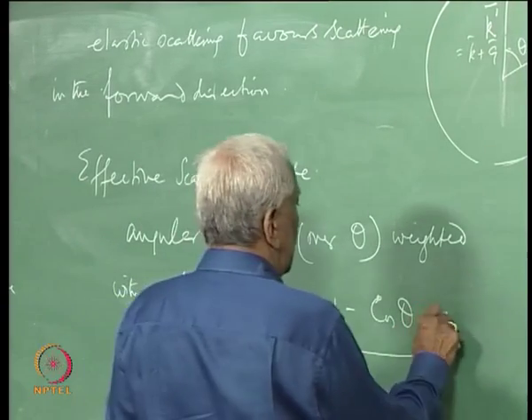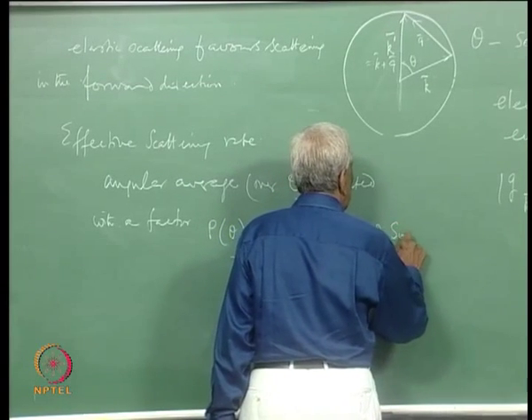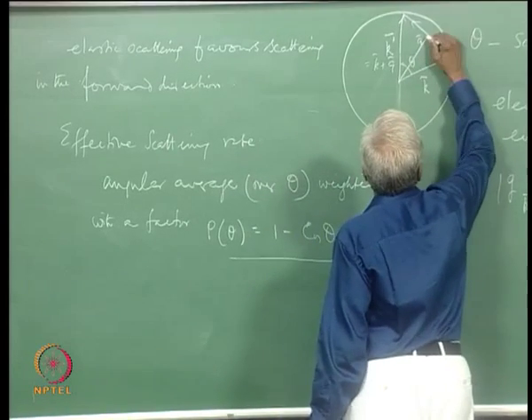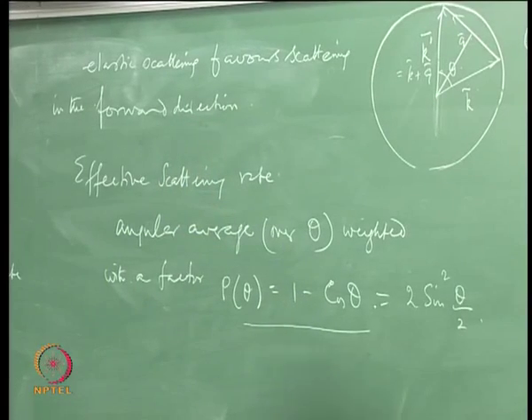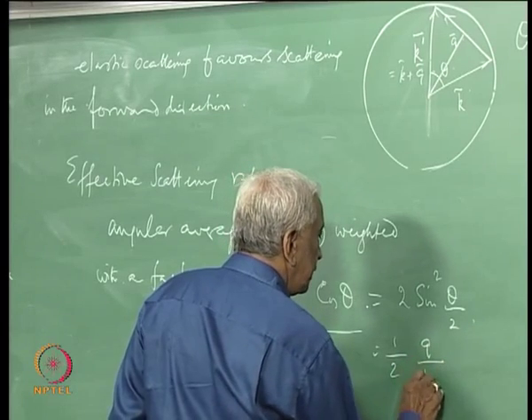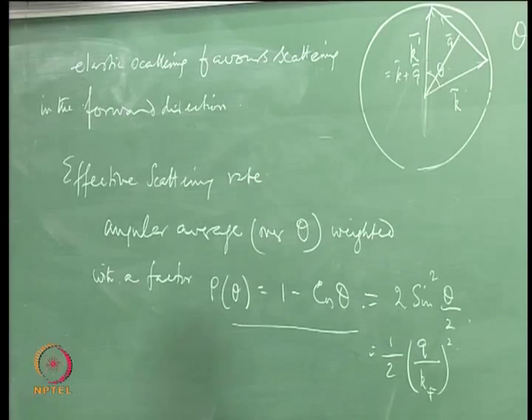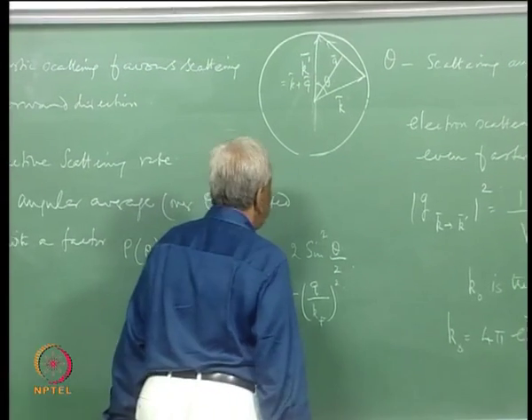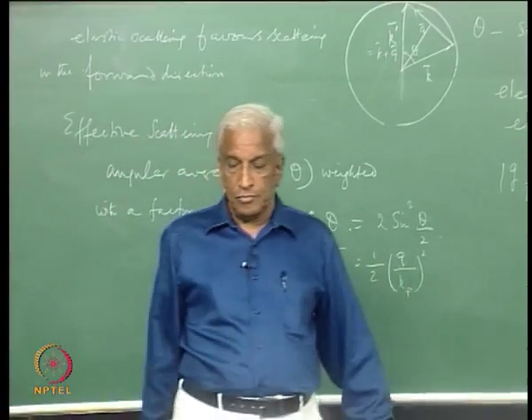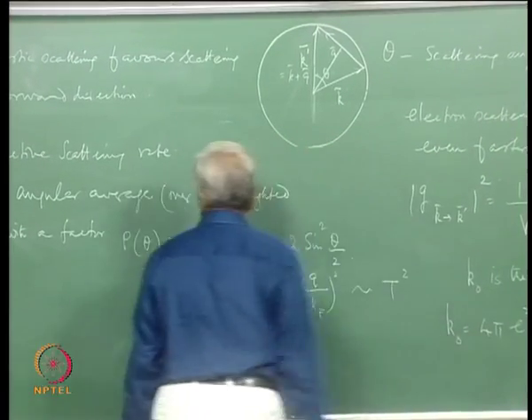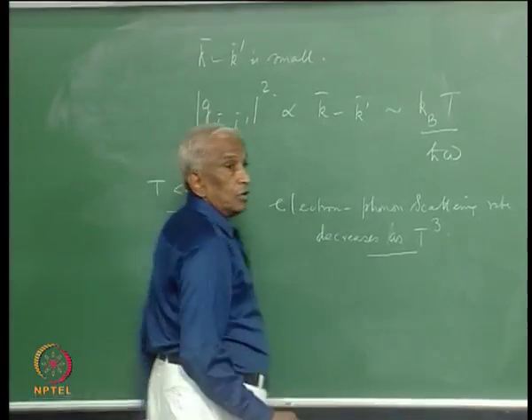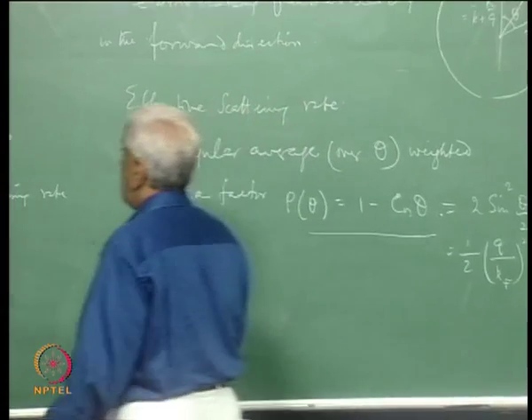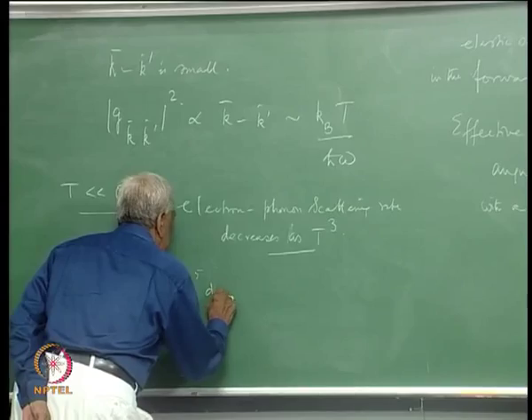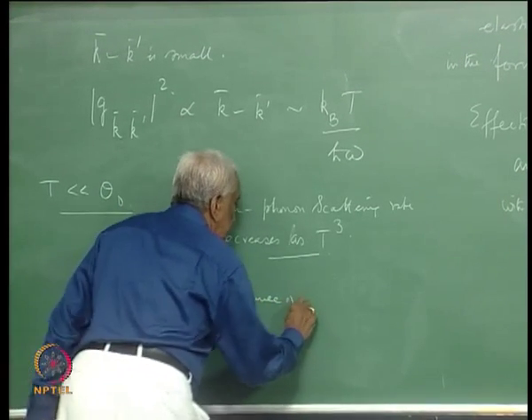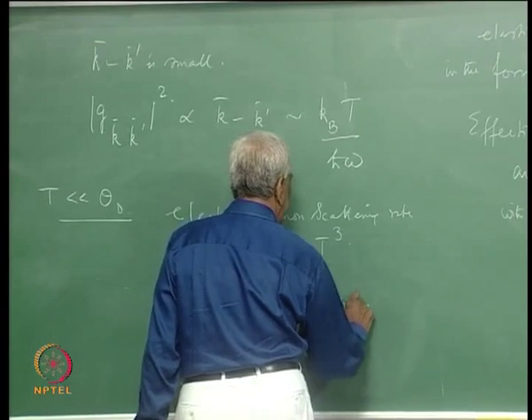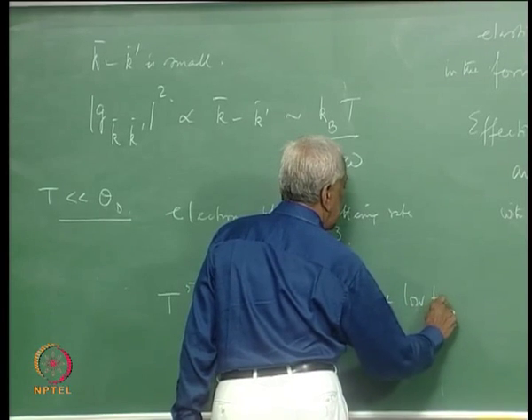And now, this factor p of theta, 1 minus cos theta, is really 2 sin square theta by 2, and you can see this situation here. So, this is really half of q by kf square, where kf is the Fermi wave vector. So, this again gives you a T square dependence. So, that combined with this T cube dependence, the net is a T to the power 5 dependence of the scattering rate and therefore, the resistivity at low temperatures.